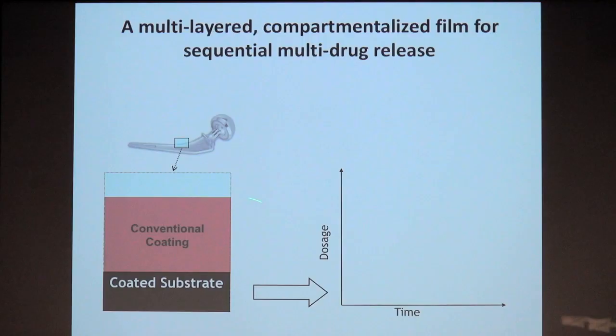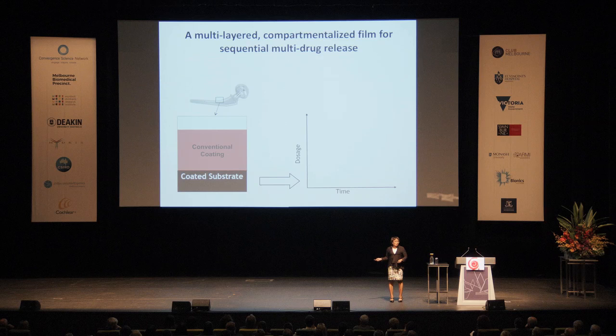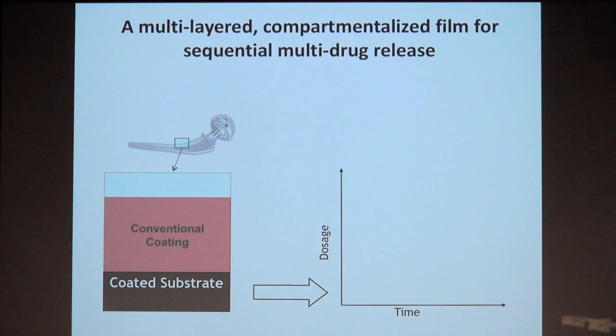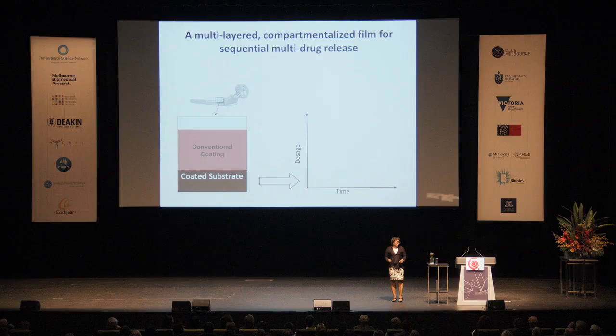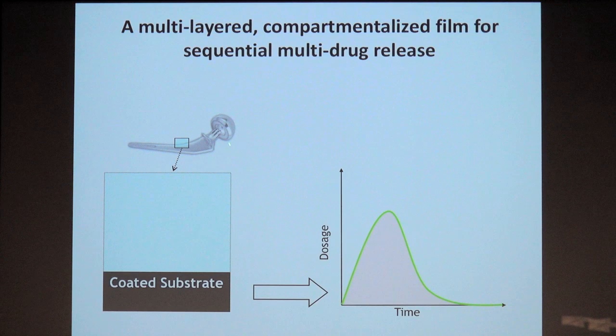One is that whenever you create a polymer coating in which you have to blend a small molecule, only a little bit of the molecule can be put into your polymer solution before it begins to phase separate because of instability. And that causes a system that releases everything at once instead of in a controlled fashion. So I can't put a lot of drug into a polymer coating. And if I need to deliver a lot of drug, I have to have a really large, thick coating, which can be very inconvenient and ineffective. On top of that, if I want multiple drugs in my coating, if I want them to come out in different ways, it's hard to control, and typically they all come out in the same way. This is okay for some applications, but in other applications, I may want one drug to show up early and one drug to show up a little bit later. Now, this is an example of a coating that might go on an orthopedic implant, one can imagine. This is actually a sketch of an orthopedic hip implant.